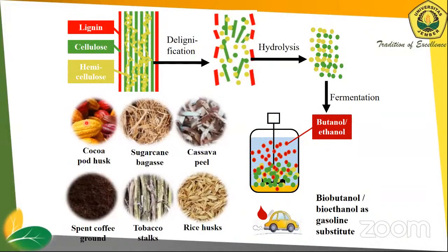This is the process of converting the biomass. We have to degrade the lignin using delignification, then hydrolyze the cellulose and hemicellulose, and then convert the sugars by fermentation. And after that, we can get butanol, then separate it for a highly concentrated product.